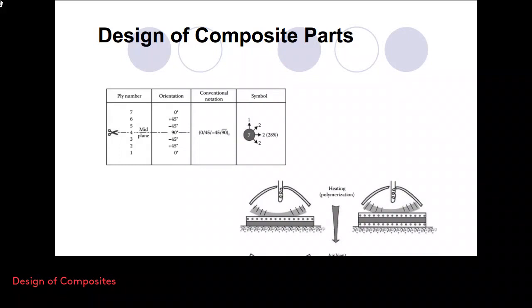Okay, we have seen how to show the configuration of a laminate. Generally, we prefer symmetric and balanced laminates. So remember that when you have a positive 45 degrees ply, there should be an equal number of plies in the other direction, so a negative 45, in order to balance the warping caused by these plies, and it should be as close as possible to the center in order to avoid residual stress-like effects because of the coupling between the shear or internal stresses, in order to avoid the internal stresses, let's say.